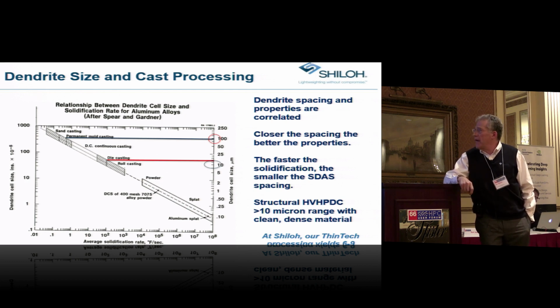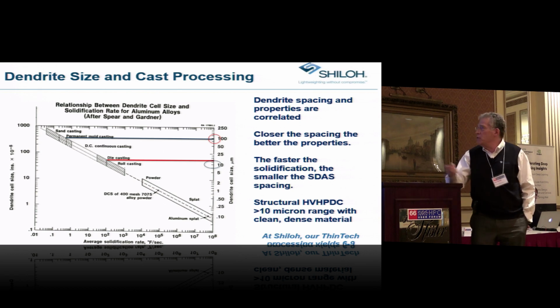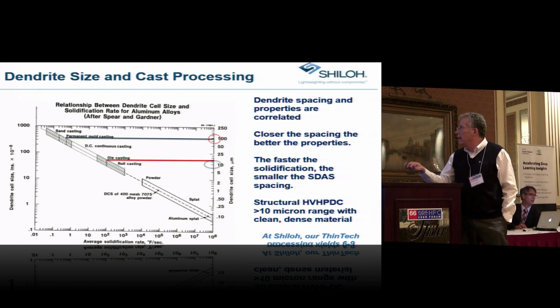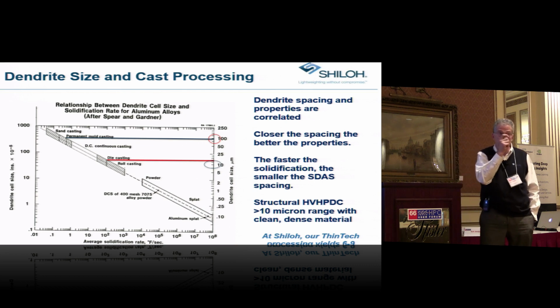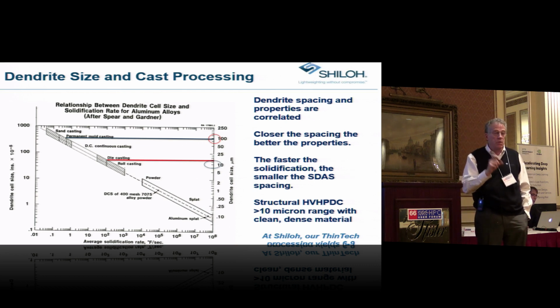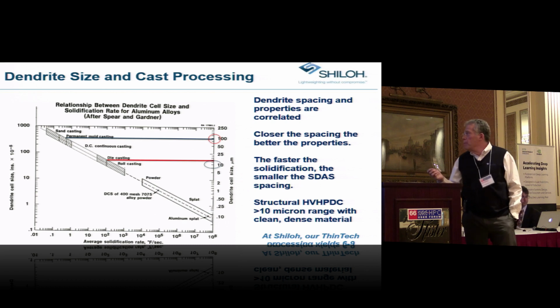If you look at some of the high pressure casting methods, we've got dendritic spacing that's down in the 10 or 12 normally, and with what we're doing with some of the new technology, we're down to 6 to 9 microns in the spacing between dendrites. So that ends up being a very good predictor of high properties, and that's one of the things we need if we're going to put these in a structural application in a vehicle.